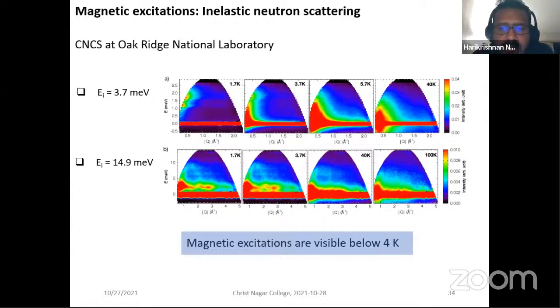Each one of those patterns is at a different temperature. If you look at the top row, you will find 4 figures at 4 different temperatures for a particular incoming neutron energy of 3.7 meV. Now you will see a conspicuous red horizontal line. If you look at the axis, you will see that it's at 0 energy. That is the elastic scattering, the neutrons which are scattered without a change in energy.